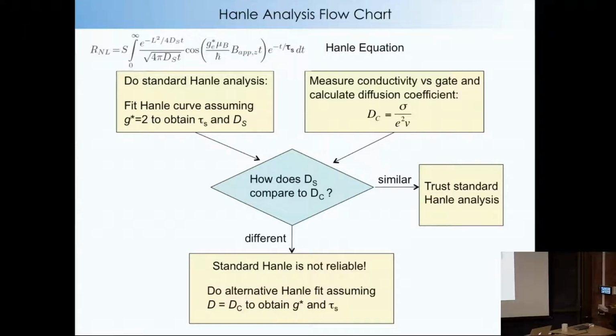There's a flow chart that is a summary of their work and our work. Here's the deal: you take the data and do the standard fitting. You assume that the G factor is 2, no exchange field, and that gives you the spin lifetime and the diffusion constant based on the spin measurement. At the same time, you can get the diffusion constant from Einstein's relation. You take the conductivity, density of states, and so forth, and you calculate this. So these are two completely independent ways to get the diffusion constant. And you ask, how do they compare?